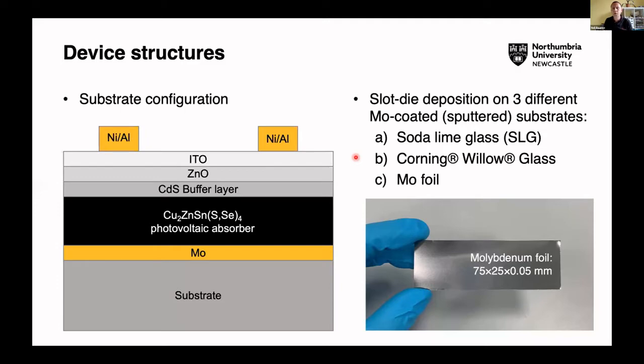So we slot die coated our nanoparticle ink on 3 different substrates: soda lime glass, Corning's willow glass, which is ultra thin, and on molybdenum foil. And the image there at the bottom shows you one of our foil substrates, which we coat directly via sputtering with a moly layer.